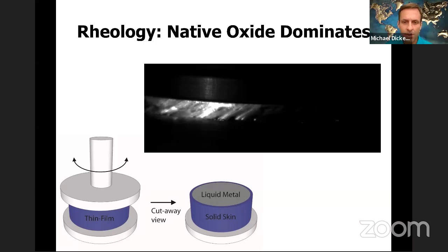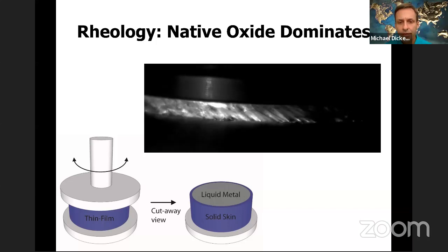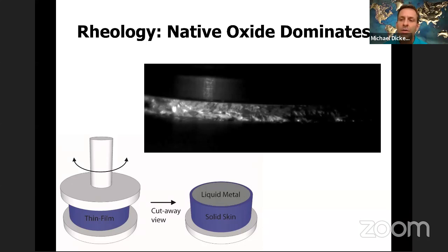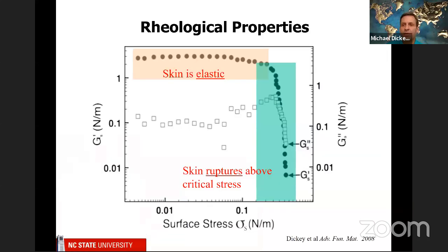So I'll show you this video. And in this video, we're going to tell the instrument to turn to the right, turn to the left, and then we're going to let it go. And it was maybe a little jittery as it played, but there's kind of two takeaways here. One is that you can see the oxide wrinkle, so you can physically see that it's there. And the other is when we let it go, it's got a little bit of elasticity to it. And so from these types of measurements, you have a plot of the elastic surface modulus. So this has units of newtons per meter instead of the usual newtons per meter squared, plotted as a function of surface stress, which is kind of how hard you push on this oxide, or I should say pull.